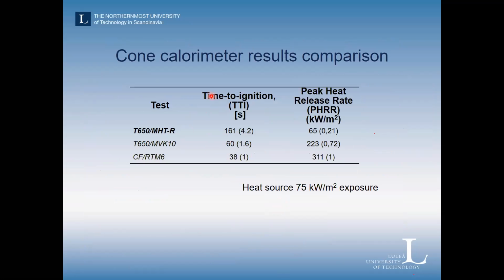So if we compare this, some of the key important aspects for the fire testing are time to ignition and the peak heat release rate. So we compare the T650 MHTR, which is the composite that we're developing. We see that for 75 kilowatts per square meter, if we increase it even further, I don't have the curves, we have a time to ignition that is 160 seconds, and the peak heat release rate is 65. And comparing it to carbon fiber and RTM6 epoxy, we notice quite a big difference here, that it's substantially better than these epoxies.